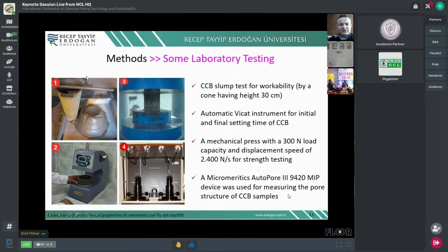We use different laboratory testing. Number 1, we use the slump Abrams cone, 30 centimeter height, and the second, an automatic Vicat instrument for initial and final setting of backfill material. Third one is a mechanical press with 300 Newton load capacity. Also, we used 2,400 Newton per second as a displacement speed.